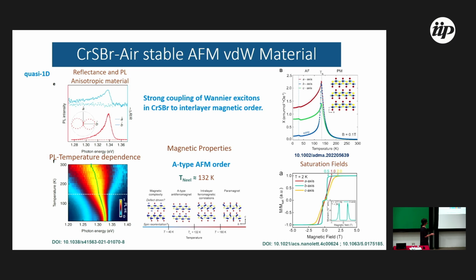So here, the magnetic properties, as I mentioned, are anisotropic. If you apply field along the easy axis, which is the B axis, you can align the magnetic moments, the spins, and you have a spin flip at around 0.3 T for a few layers. If you apply the magnetic field along the A axis, you need 1 Tesla to have this spin canting. And if you apply a perpendicular magnetic field, you need a higher field. For that reason, sometimes I need this attocube system.